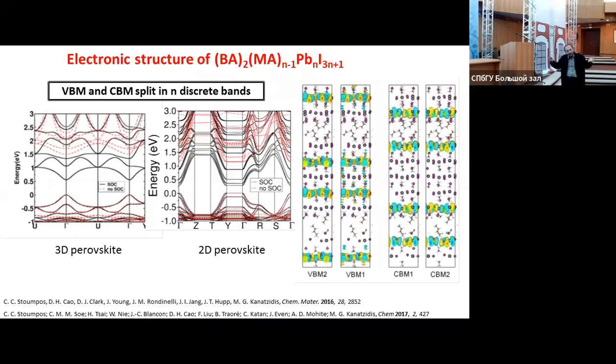From the band structure point of view, the band structure looks like this. If you consider this version of the three-dimensional perovskite, it should look like this. What actually happens electronically is we break the valence band and conduction band extrema into states, and the number of states that we break them into corresponds to the number of layers. This is the N=5 perovskite, the 5-layer perovskite. What is interesting, but I'm not sure at this point if this is an artifact from the DFT calculation or not, is that the valence band seems to localize in the middle layers, 2 and 4, the second and the fourth layer of the quintuplet, but the conduction band localizes at the edges.